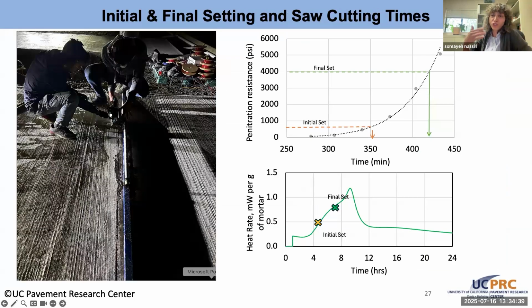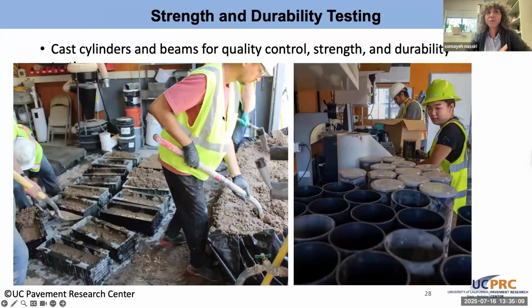And then we are trying to come up with a method to then cut the joints in a timely manner with respect to final set time, with respect to the cement hydration development, so we can minimize the amount of raveling that otherwise may develop across the joints as they're being cut, because this is one of the points of an area of weakness. And it could be one of the Achilles heels of concrete pavements along the joints if they're not cut in a timely manner.